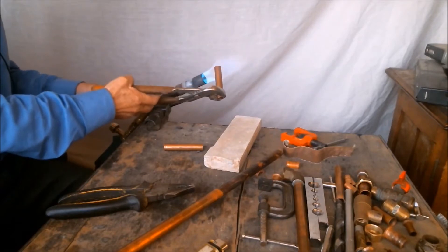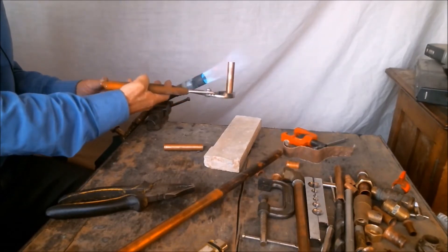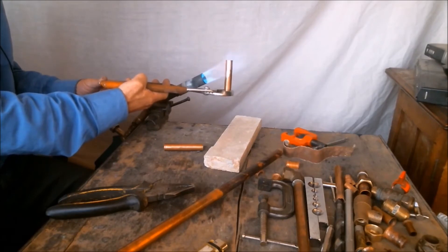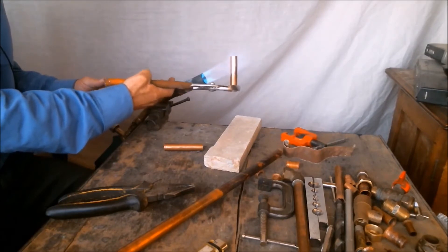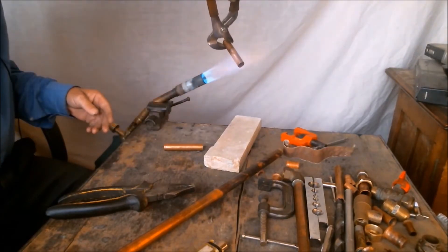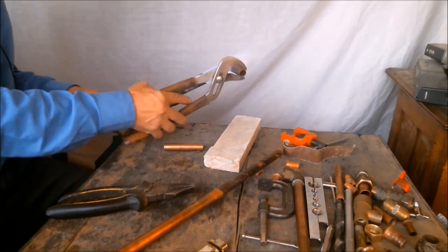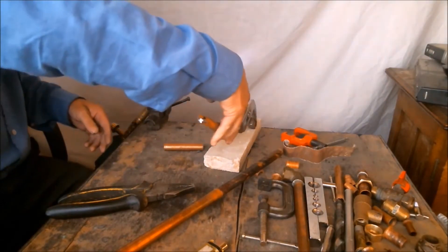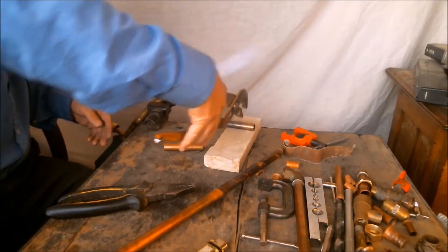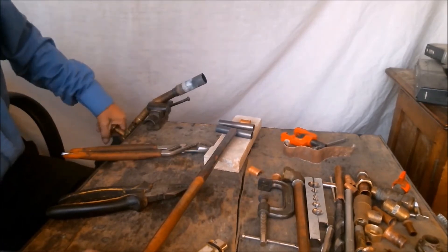Now we must anneal the pipe, heating the copper with our torch and covering at least 2 inches from the end, depending on the size of the pipe. It must get completely red hot all around the pipe. Then we let it cool off slowly on a heat resistant surface.